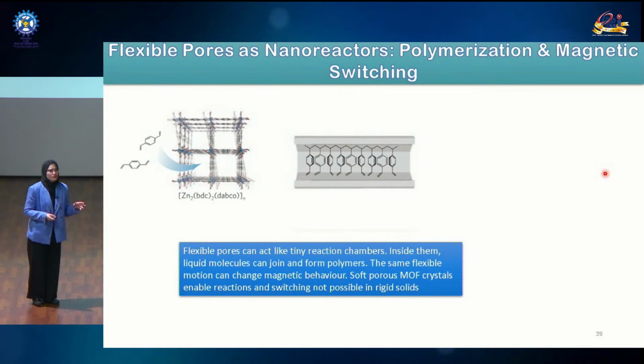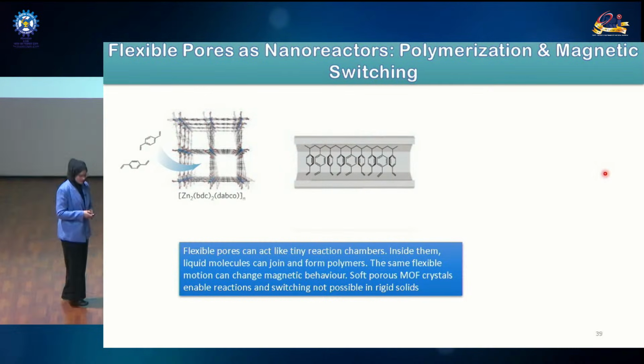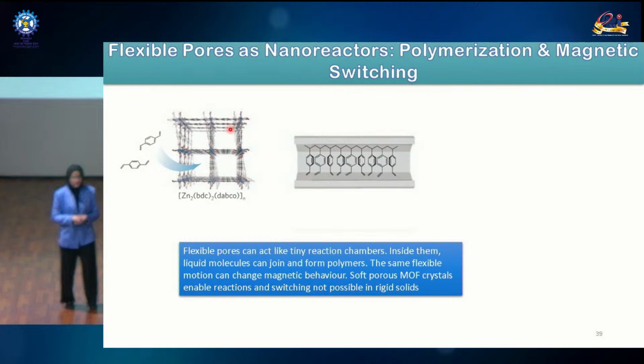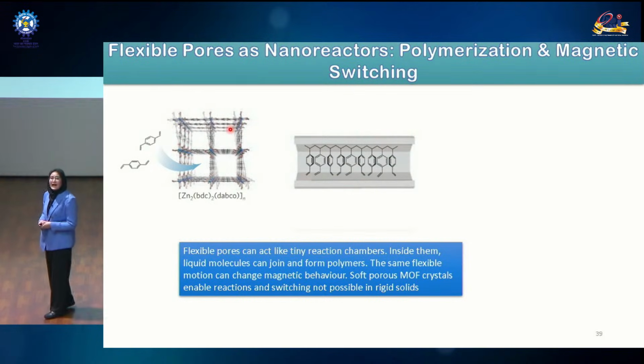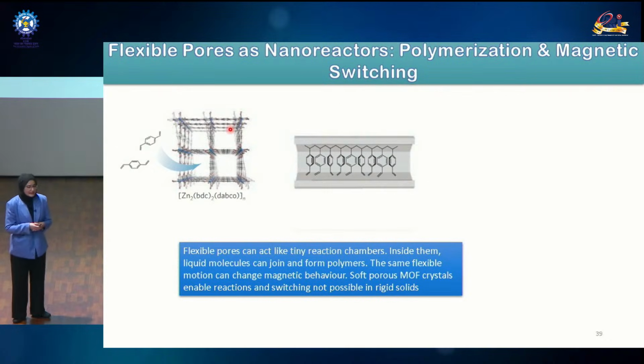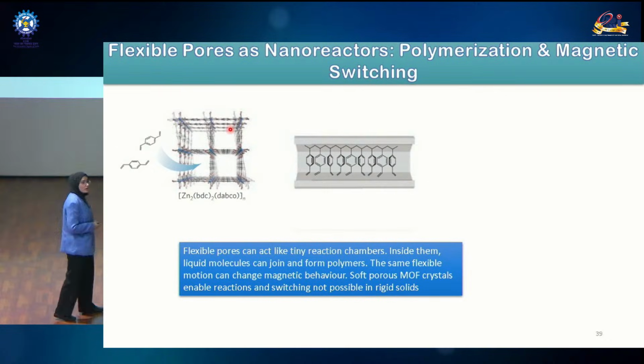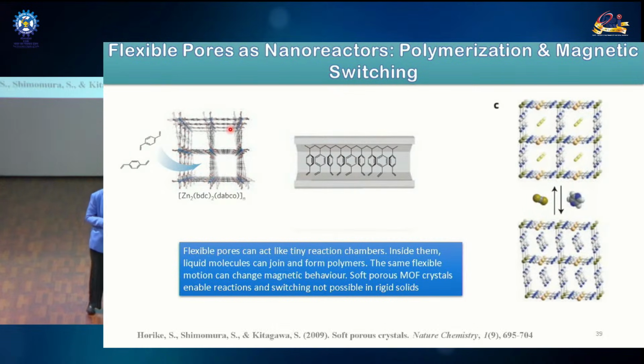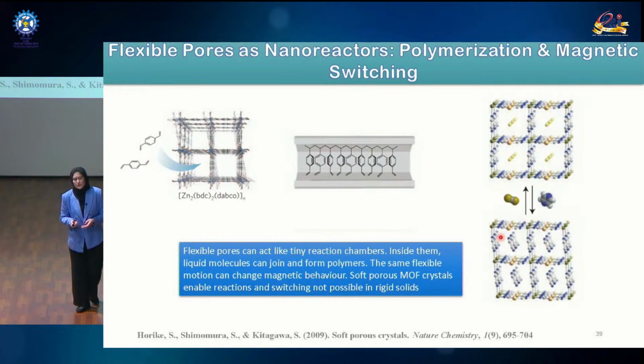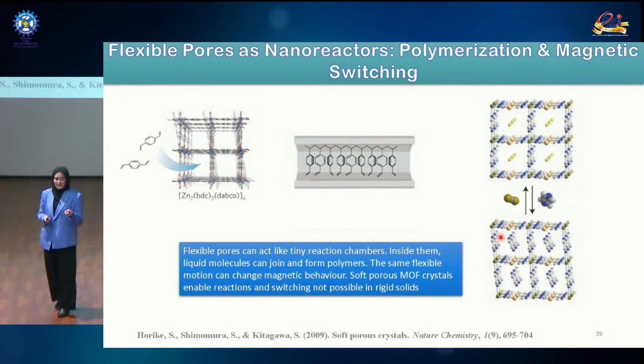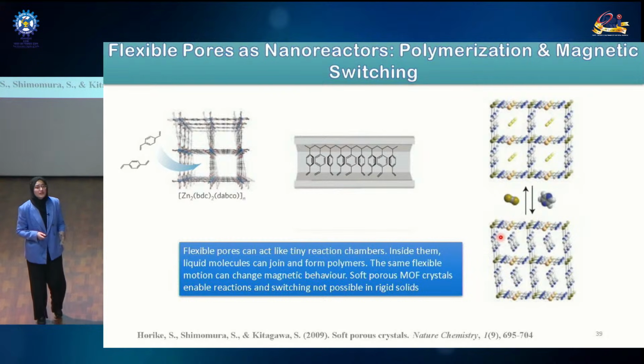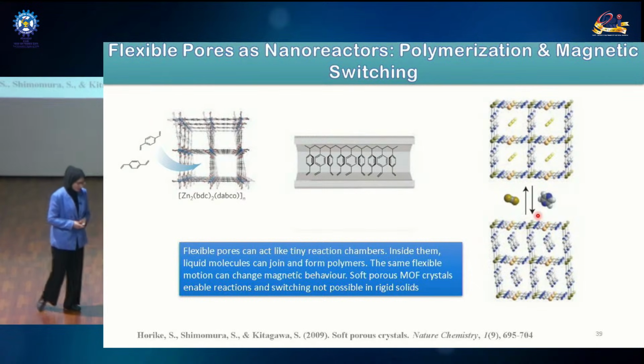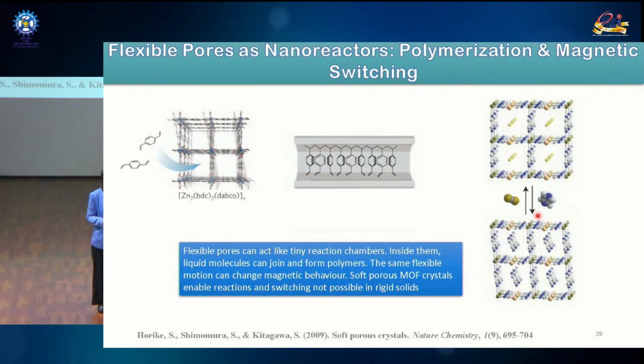Now this slide shows two unique functions which only came from Kitagawa's MOF crystals. The image shows the polymerization inside a flexible MOF. Because these pores are flexible, they can act like tiny reaction chambers. Inside them, small liquid molecules can join and grow into polymers in a controlled way. On the right, the image shows the magnetic switching. When a framework breathes, that is, opens and closes, it changes its electronic environment as well. This breathing switches a magnet on and off. Both of these functions were not possible in rigid MOFs. They only happen when Kitagawa made these crystals flexible.